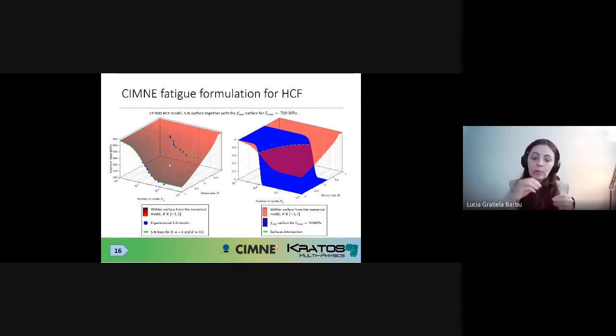will have points that throughout the nonlinear process will change, will go away from that SN curve, which is specific for -1. If you have a model which only takes into account discrete SN curves, you are going to be in an indetermination if you are going away from that specific SN curve. This is why it's important to have a continuous, well-defined surface of stress number of cycles curve. And this is what we are doing inside our formulation. Here you can also see, for instance, what the reduction surface looks like when you intersect it with the SN surface for a specific level of maximum stress of 700 megapascals.